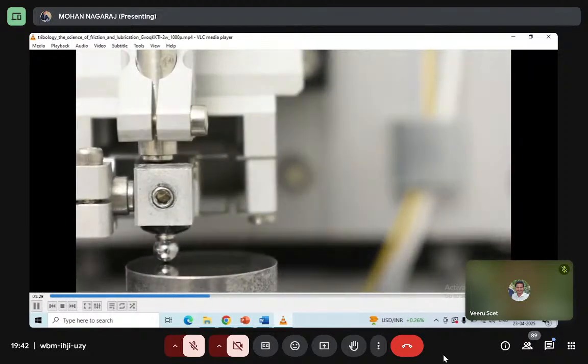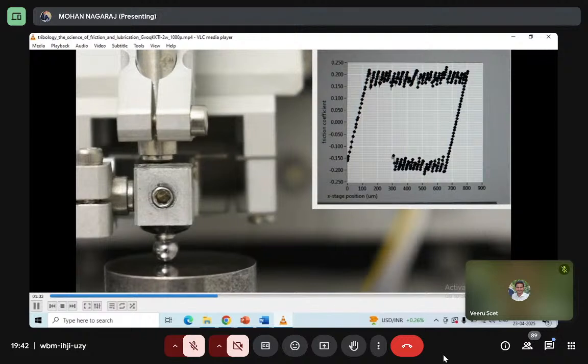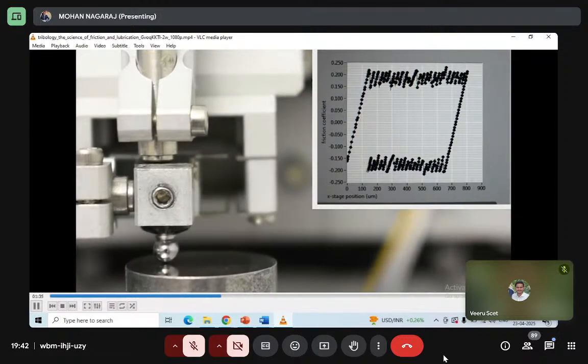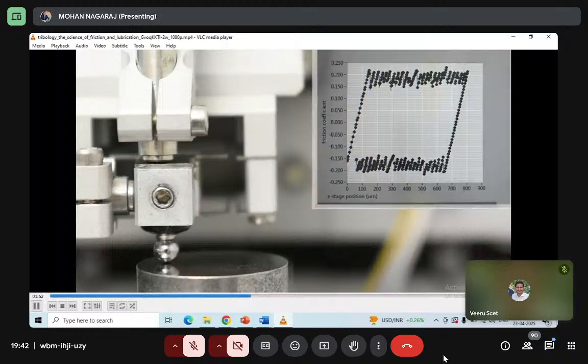As the ball rubs across the surface, data is being collected. At every location, we are getting the coefficient of friction. For example, at one location, the friction coefficient is around 0.17, and at another location, it's 0.15. Altogether, the data shown tells us the average coefficient of friction is around 0.16 for the surface.